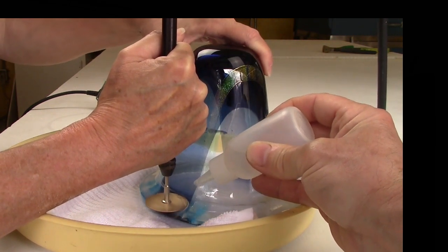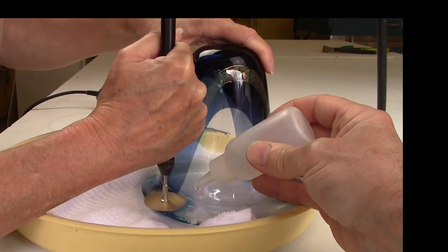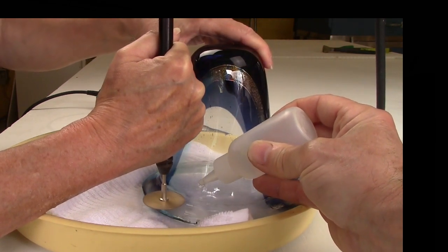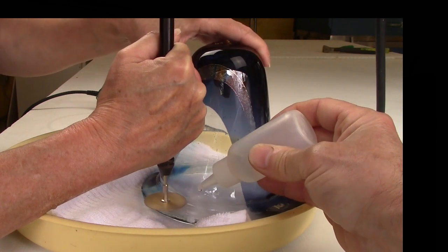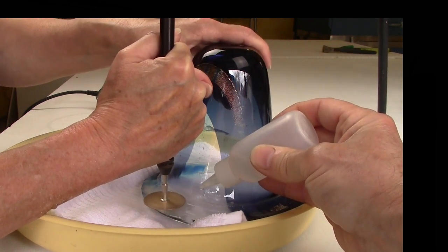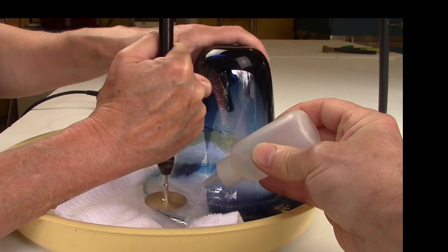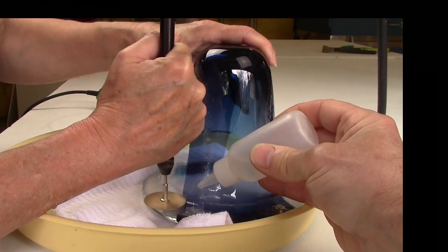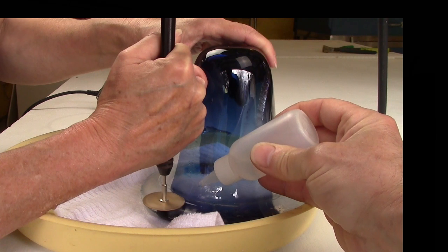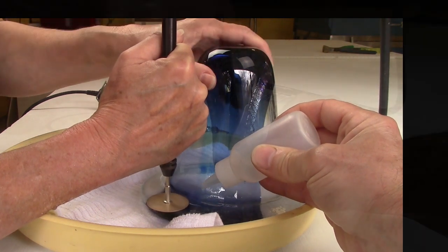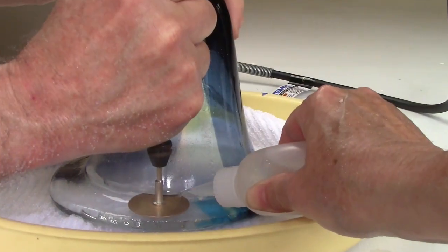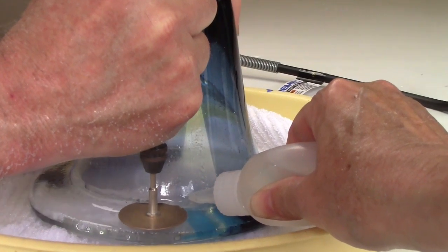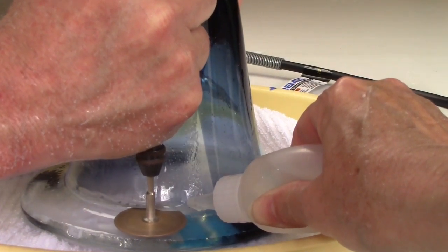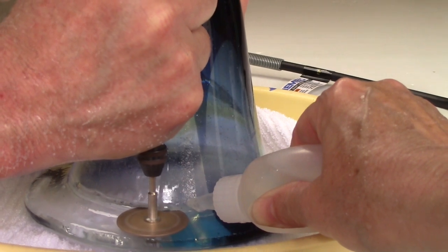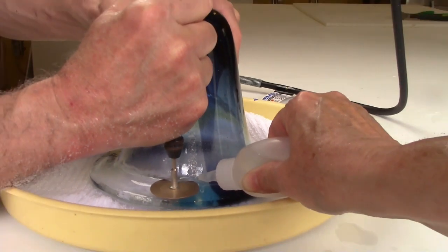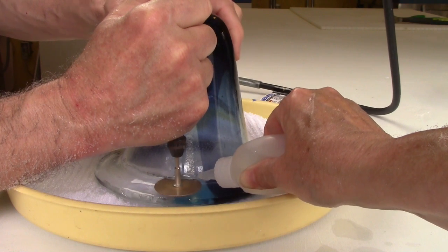Anytime you're cutting or grinding glass, you want to make sure that the glass and the tool are well lubricated. It keeps the dust down, it ensures that your tool lasts longer because it'll remain sharp, and it reduces heat and friction on the glass, which gives you a better cut. So here we're using a little bottle to squirt water on that slitter while we're cutting through the glass. You go slow and steady, just take your time, go around multiple times, removing a little material here and there until you actually cut through the glass.